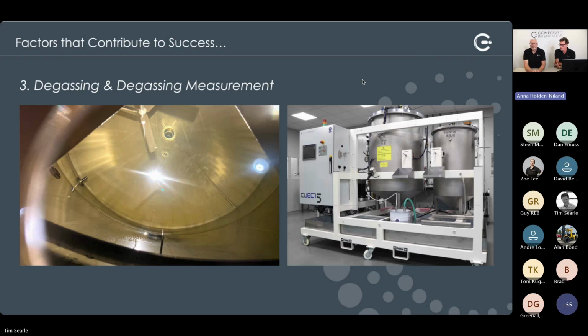And if we look at this next slide, here's some of the equipment that incorporates that technology. And the image on the left is taken from the top of the bigger of the 2 tanks you can see on the machine. The tank's around 2 meters tall, and there's around 1.5 meters from the top surface of the resin to the bottom outlet fitting you can see in the bottom of that tank.